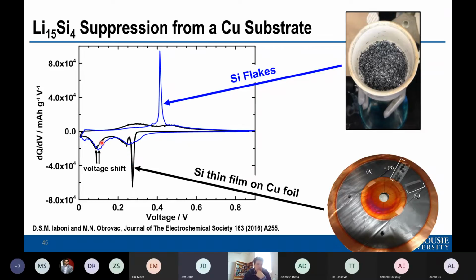The other thing you see is the voltage is shifted, just like you would expect for a thin film, because of this stress voltage coupling. And you no longer see the 15-4 phase because this peak has been shifted to a potential where you never reach it. We cycled down to 5 millivolts, and this thing must have been shifted below there. We never saw it. And now you don't get 15-4 formation anymore, which is good because, again, this two-phase region you want to avoid, because that's where you have these phase boundaries in your particles, where there's a lot of stress and things that can cause cracking.